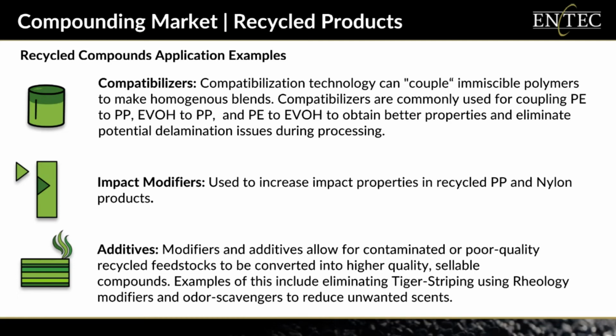In another example, a compounder was offered a very low-cost polypropylene feedstock that contained 2 to 3% EVOH contamination. They tried to compound the material but had major processing difficulties. Adding a maleic anhydride modified polyolefin compatibilizer to their formulation allowed them to produce a high-quality compound. This allowed them to utilize this low-cost contaminated feedstock rather than potentially having to send it to a landfill.